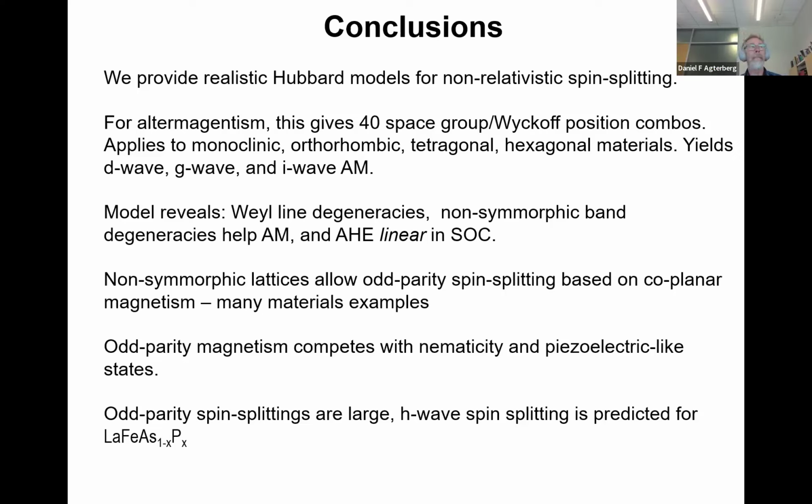So no real materials will have these quasi-symmetries, but what we can answer, let me see if I can go back to my slides to show. Okay, let me explain. What we're interested in is, does the ferromagnetism appear to linear order in spin orbit or not? What we can show is that the quasi-symmetries tell us that to linear order in spin orbit, there is no ferromagnetism, and it must appear in higher powers in spin orbit.